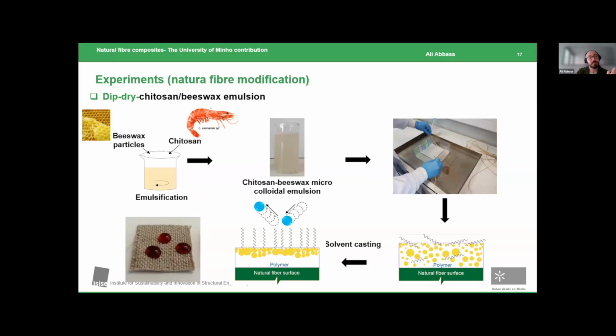So we would take this chitosan polymeric formulation. We would heat it up to the melting point of the beeswax particles. Beeswax particles perform as a fatty acid here. So they are the superhydrophobic molecule that we want to deposit onto the fibers. So we emulsify at the melting temperature of the beeswax. Then we obtain this emulsion, and we carry on, as you can see here, the coating. So we dip, then we solvent cast through heat treatment. Then we have this beautiful aliphatic superhydrophobic tail of the beeswax protruding outward of the surface and repelling the water, resulting in a superhydrophobic textile reinforcement.